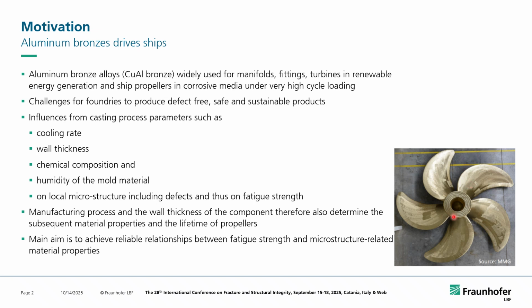So we have different wall thicknesses here next to the middle of the propeller and to the tip of the blades, having different wall thicknesses from several 100 millimeters down to several 10 millimeters. So the cooling rate will be different due to the wall thickness, and in combination with the specific chemical composition, we might have then also different microstructures in the different areas of a propeller.